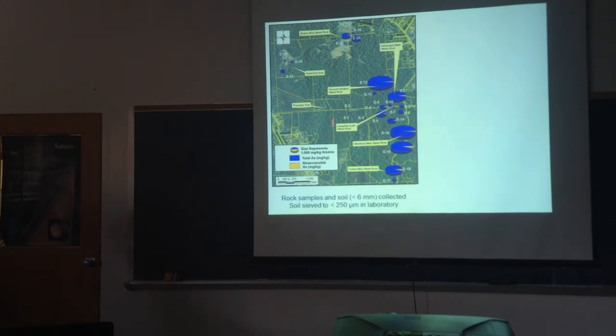This is another map that shows the distribution of arsenic. The bigger the circle, the more total arsenic. And bioaccessible arsenic is this little sliver. So you can see that most of the sites we looked at had very low percent of bioavailable arsenic, but because the total arsenic was so high, you know, 10% of 10,000 ppm is still 1,000 ppm of bioavailable arsenic. That's still way too high. So even though it wasn't that bioavailable, you still had to do something about it.